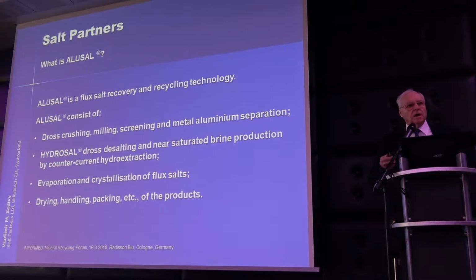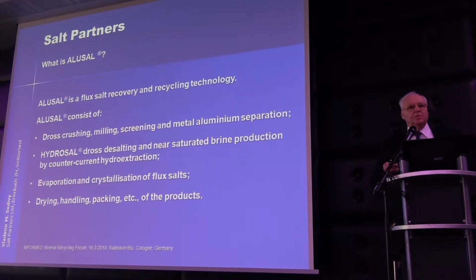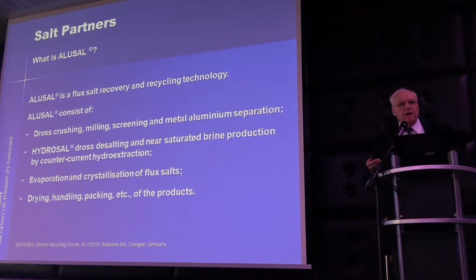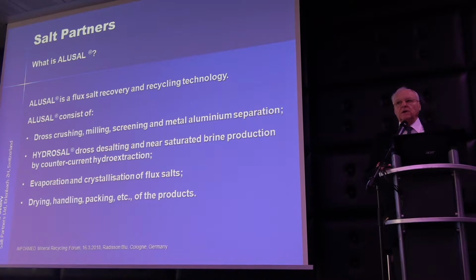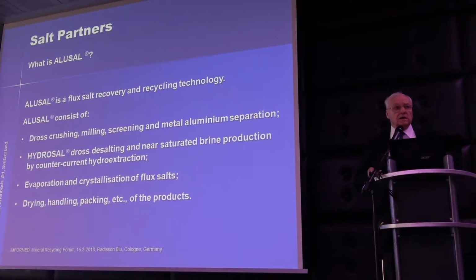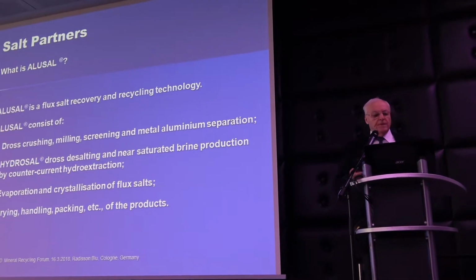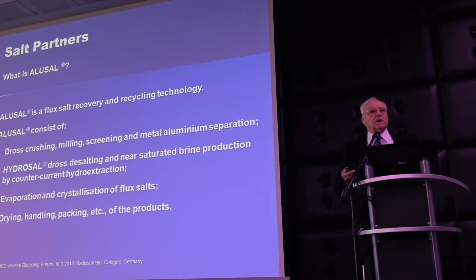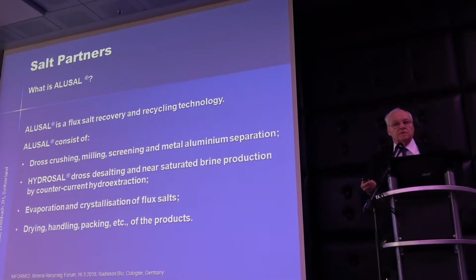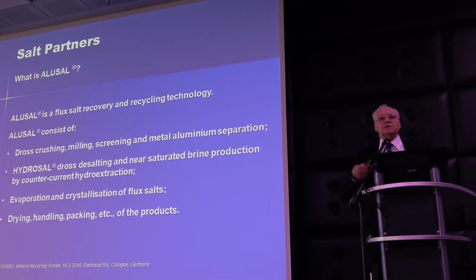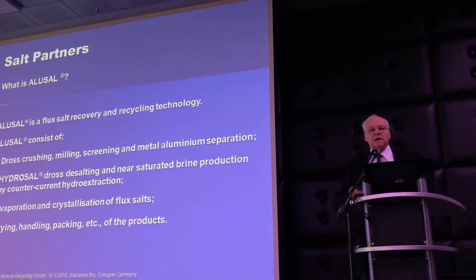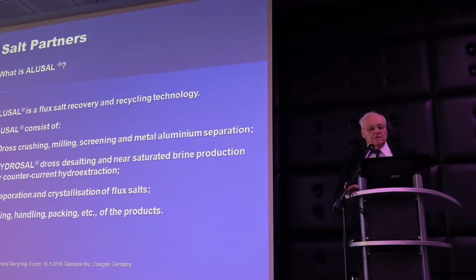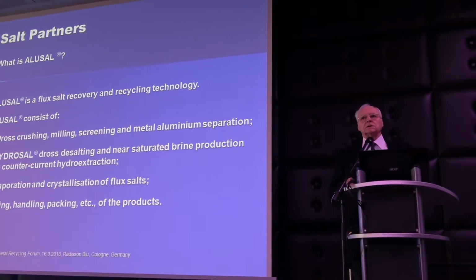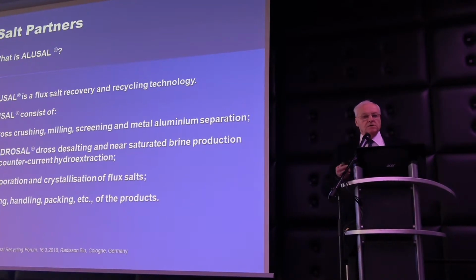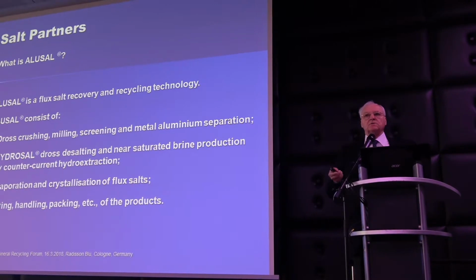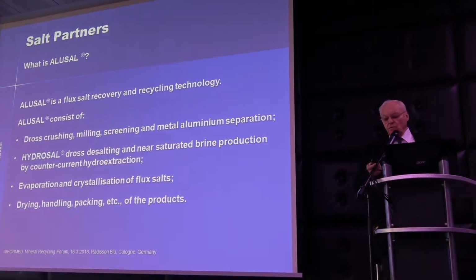So we said, okay, our countercurrent continuous process should be capable of, on the one hand, producing a really salt-free slag, and on the other hand, producing a near saturated sodium chloride solution. The solution then goes to an evaporator and crystallizer, and there, if the solution is diluted, you have to first evaporate water before the crystallization starts, and that makes the whole process much more expensive. It's the main energy, the steam or electricity consumption, that is taking place here. So, on the one hand, slag without salt, on the other hand, near saturated solution for crystallization.